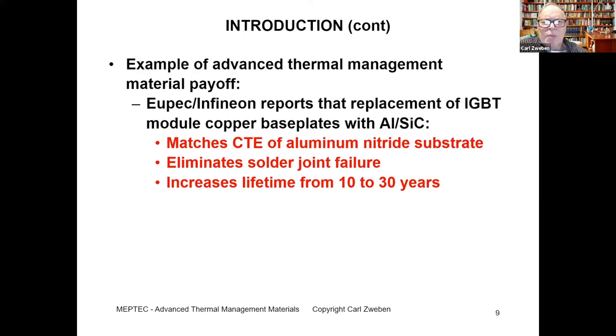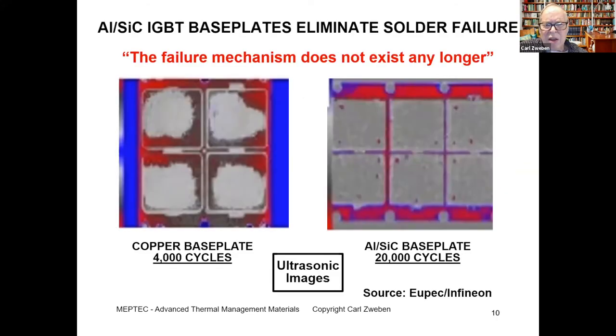So here's one example of the payoff from using advanced thermal materials. Eupec/Infineon report that replacing a copper base plate in an IGBT module with AlSiC, which is aluminum reinforced with silicon carbide particles, matches the CTE of the aluminum nitride substrate, eliminates solder joint failure, and increases the lifetime from 10 to 30 years. So here's an ultrasonic image scan of the baseline copper base plate on the left.